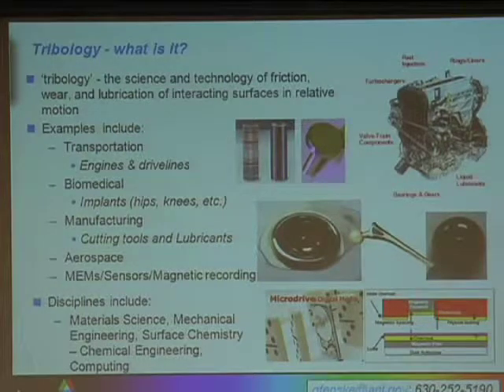Biomedical applications is another thing. Hip joints, knee joints, and jaws, and finger joints, and so forth. Quite a large number of operations are done each year to insert artificial hip joints and so forth. And again, tribology is a critical thing. One of the areas how these things start to fail is that during the wear process, you generate a lot of small individual wear debris inside the body, and your body looks at those wear debris particles as foreign bodies, and they try and resorb and get rid of that wear debris, and in the process they start to dissolve it, but they also dissolve the bone and so forth, and so you end up with the failure of these systems and you have to get them replaced.